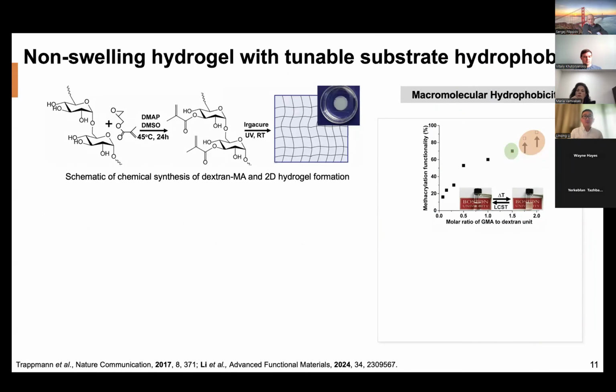So the first question we are trying to address is how to develop a hydrogel platform using this material. To that end, we resorted to the literature, which widely uses modification of the backbone through the hydroxyl group with methacrylate groups through a one-step modification. Once you go through this modification, you achieve methacrylate-modified dextran. Because it has unsaturated double bonds, we can use photocrosslinking to form the hydrogel.